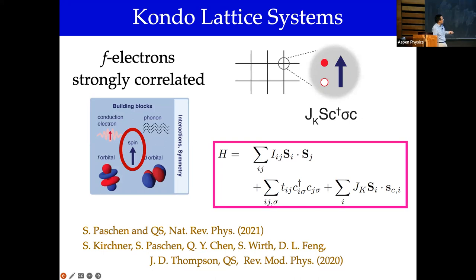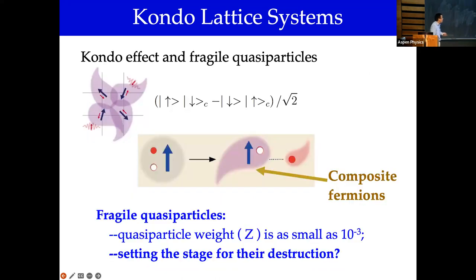And then there are spd electrons which live on the fast lane, represented by conduction electrons. Symmetry dictates that the spins of the f electrons can interact with the spins of the conduction electrons. We call this a Kondo coupling, which turns out to be antiferromagnetic. So there's the magnetism of the spins, the conduction electrons associated with the spd electrons, and the coupling between the two. In essence, that is a relatively simple characterization of the microscopics. But it turns out that there's a piece of physics which connects with the formation of the quasi-particles, that sets a stage of breaking them.